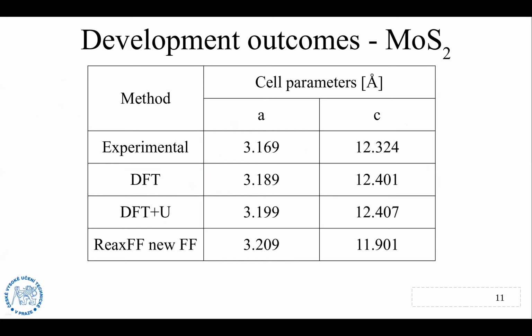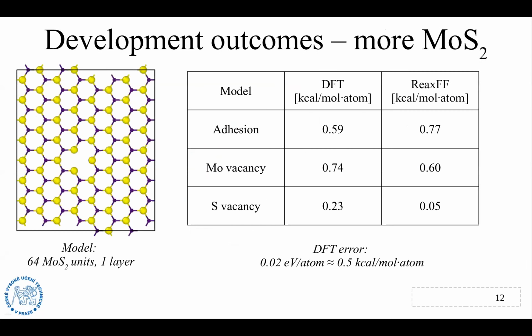So cell parameters of MoS2 was another test. And again, we are within reason from both experiment and computations within DFT. Some defective structures and adhesion of layers were also at least within the margin of error that one would expect from the DFT values.